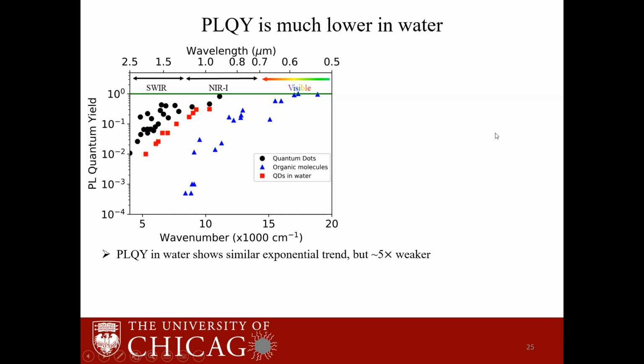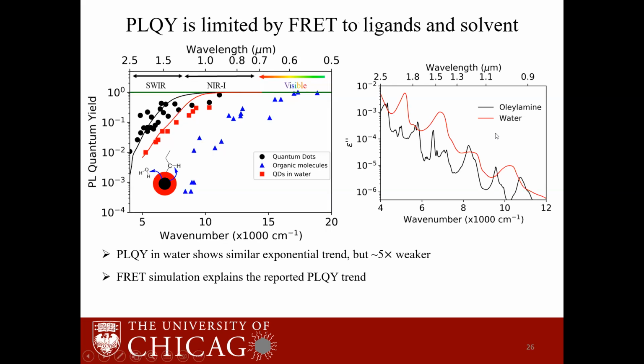And this is something that hasn't been discussed or explained before. So motivated by our previous work on the fact that ligand FRET is the dominant relaxation for quantum dots at 5 microns, we have calculated the rate of FRET between the quantum dot and the ligands, as well as quantum dots to solvent molecules. The calculations are these solid lines, and we can see that the calculated trend matches fairly well for both the organic capped quantum dots, as well as quantum dots solubilized in water.